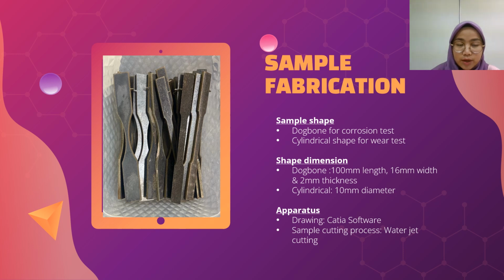The shapes for the samples are dog bone for the corrosion test and cylindrical shape for the wear test. The sample dimensions for the dog bone are 100 mm length, 16 mm width, and 2 mm thickness, while the cylindrical sample has a 10 mm diameter. Apparatus used are CATIA for sample drawing and a water jet machine for sample cutting.